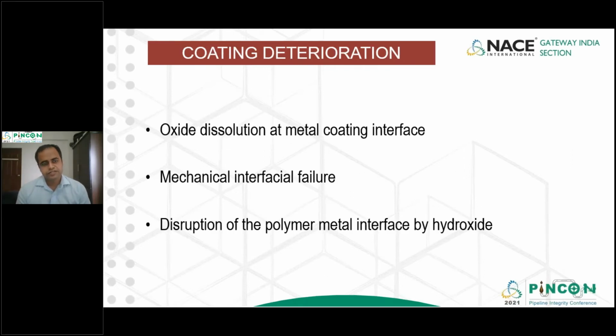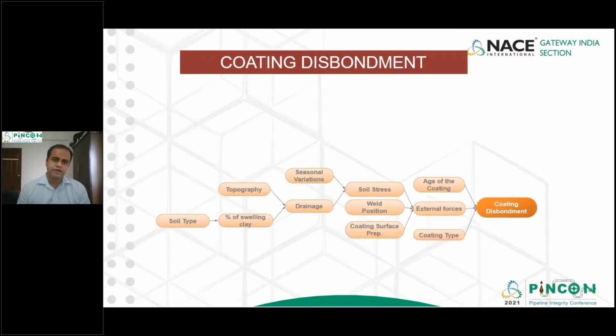What happens when a coating deteriorates? Basically, the oxide dissolution at the metal-coating interface, the mechanical interfacial failure, and the disruption of the polymer-metal interface by the hydroxide. I hope the audience is aware, because these are very simple phenomena which happen because of coating deterioration. Now, when a coating goes for disbondment, a lot of factors which I could identify have been tabulated here. One of them is the soil type, the topography, the percentage of clay, the drainage, the seasonal variations, including the weld position of the pipe, the coating surface preparation, be it in the field or in the factory, and further the aging of the coating, the external forces which are at play, and the type of the coating. These are the few factors which I could attribute to the coating disbondment.